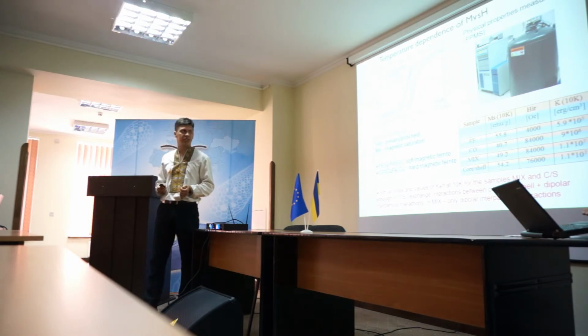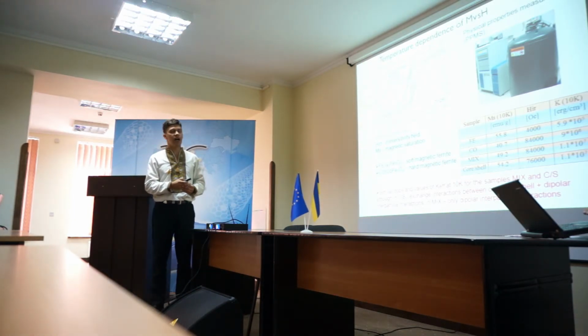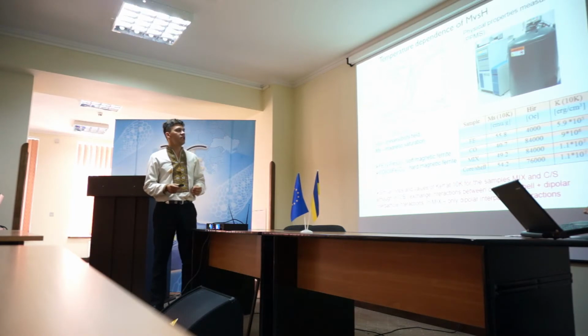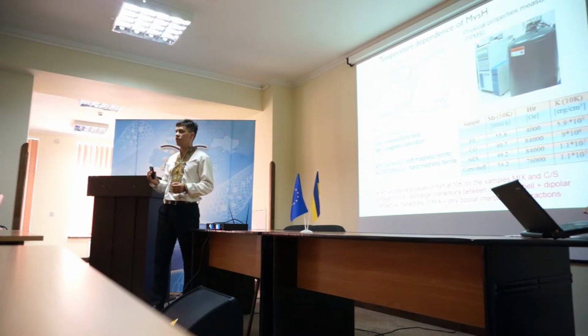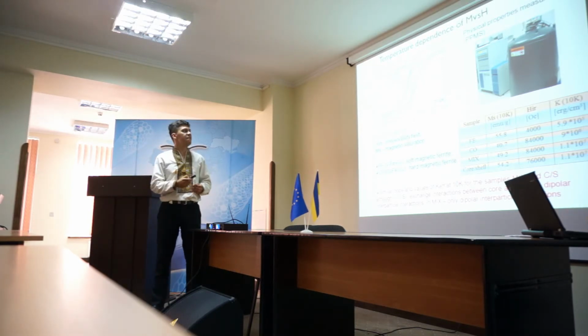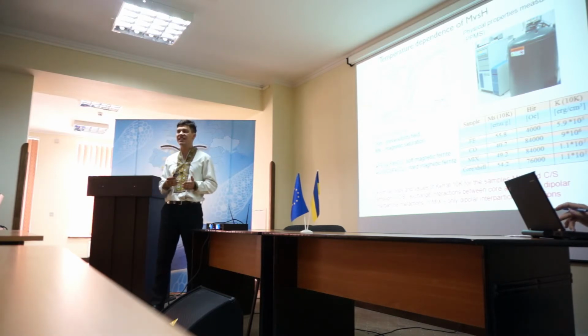All magnetization measurements were done using the Physical Property Measurement System, PPMS, produced by Quantum Design. In this picture we can see the hysteresis loops. The red loops are the cobalt ferrite nanoparticles, a hard ferrite magnetic material with high coercivity and high magnetization, but for cobalt ferrite this magnetization significantly decreases when the size of the nanoparticles decreases. It's due to the content of the spins on the surface of the nanoparticles. In opposite, the green loops are the manganese ferrite, a soft magnetic material without coercivity and with high magnetization, and this magnetization is not significantly decreased when we decrease the size of the nanoparticles.